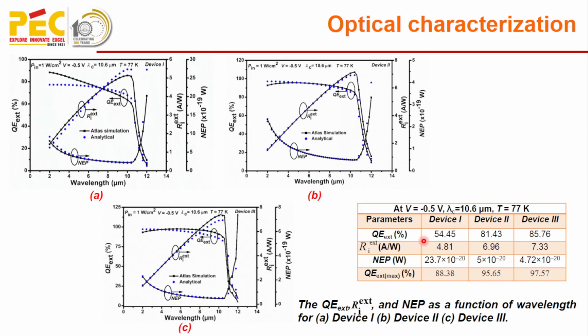Now, optical characterization. For optical characterization, we have studied the quantum efficiency, external photocurrent responsivity, and noise equivalent power. It is clear that the quantum efficiency, noise equivalent power, and external photo responsivity perfectly match with the analytical modeling. Here we can see the parameters which we are getting. Device 3 shows a high quantum efficiency as compared to device 1 and device 2. This is due to the presence of a huge electric field at the heterojunction, and a low value of noise equivalent power is desirable so as to achieve the best performance, meaning it is a highly sensitive photodetector.